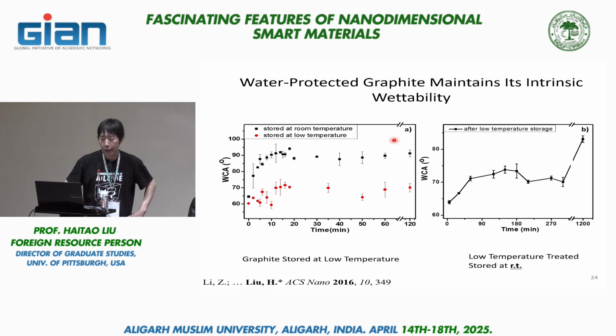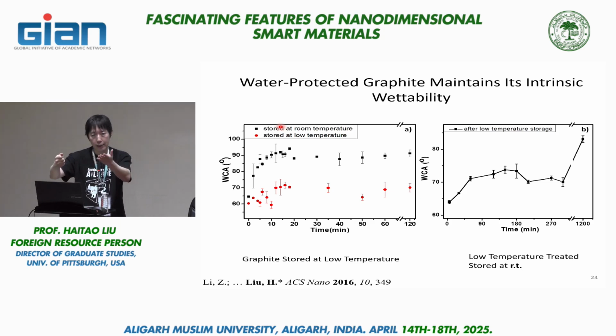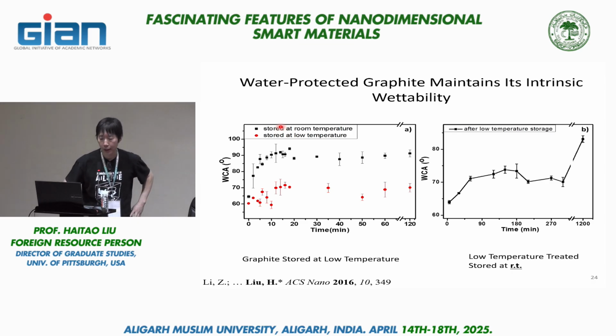Now, if I do the exfoliation of graphite and I immediately put it into dry ice temperature, I just store it around a bunch of dry ice, and then you take it out periodically to do the contact angle measurement. Surprisingly, you find in this case, the contact angle doesn't increase as fast. Instead, it simply fluctuates between 60 and 70. So it doesn't increase anymore.